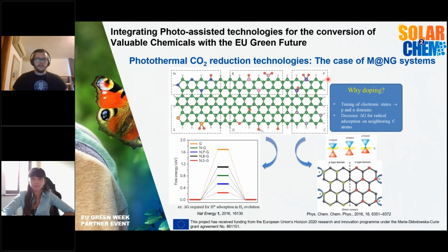Why graphene though? Well, at least in our system, it is very convenient since both the d bands of the metallic species and the pi bands of the graphene can interact synergetically to give quite outstanding catalytic results. And moreover, with the doping that I previously mentioned, we can help a lot with substrate capture, which enhances the catalytic output quite a lot.